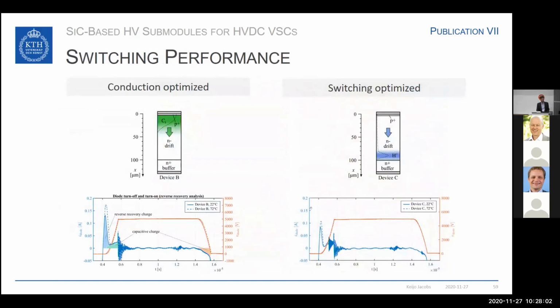Now I'm going to go into detail with the switching performance of these devices. On the left side, you can see the conduction optimized device, which is device B. On the right side, you can see the switching optimized device, which is device C. You can see here the reverse recovery effect as shown already schematically before, but this is a measurement. You can see that the reverse recovery peak for the conduction optimized device is much higher than for the switching optimized device. And you can also see that the current tail for the switching optimized device is much shorter.